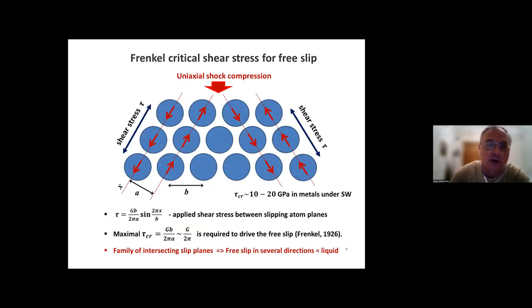Okay, a few words about the Frenkel critical shear stress. It can be reached in uniaxial shock compression of the lattice. Then the shear stress is mostly oriented at about 45 degrees between atomic planes. And this shear stress can be expressed in a simple equation. The sinusoidal equation is, of course, an approximation using the shear modulus, so it depends mostly on the shear modulus. If we assume that the interatomic distance and the interplane distance are almost the same, then we have such a simple expression. In many metals, such critical shear stress is in the range between 10 and 20 GPa, of course, under shock compression.